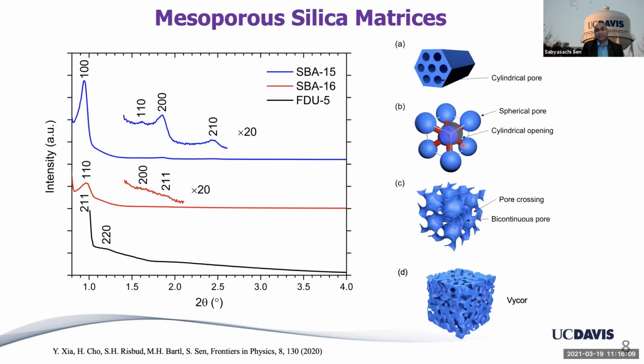Then these are SBA16, which have these spherical pores attached through cylindrical openings, shown in red. FDU5, which has a sort of bicontinuous lattice of cylindrical pores. So there are cylindrical pores, and then at the junction, there are spherical junctions between these cylindrical pores. So two sizes, one is the spherical pore size, another is the cylindrical pore size. Here also there is a spherical pore size and a cylindrical pore size, but these are all interconnected. So the liquid, if it wants, can go and visit the other, adjacent channel.